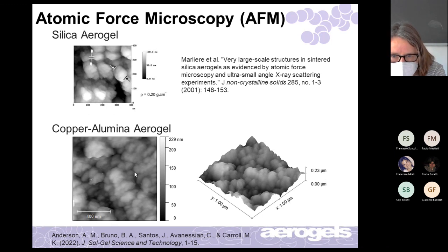The student who did this had to figure out how to adhere the aerogel to the surface without having it move, because you take the probe and move it across the surface, and sometimes when you do that you'll see some smearing, maybe here. So he used nail polish, what people put on their fingernails, which he found would attach it well. So that worked well, and we were happy to get this sort of information.